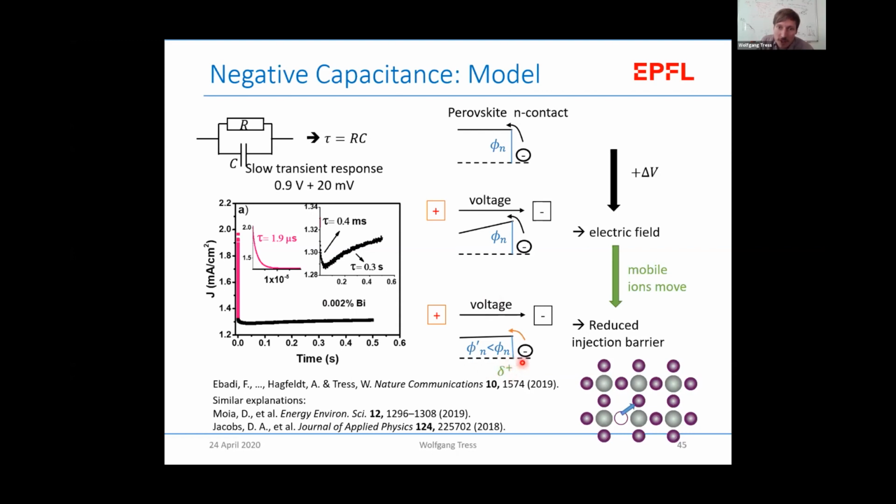And this positive charge can form in principle a dipole, reducing this barrier and making it much more likely that this electron gets injected. So we don't see that for this effect we had to generate a gigantic or a negative capacitance, but what you see is that we made this process more likely, which reduces the resistance slowly.